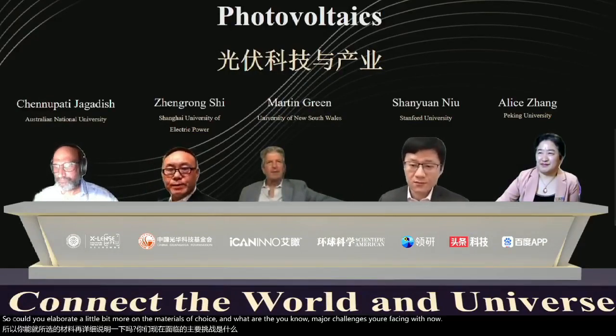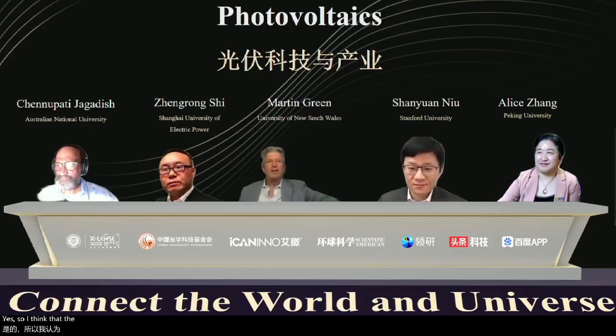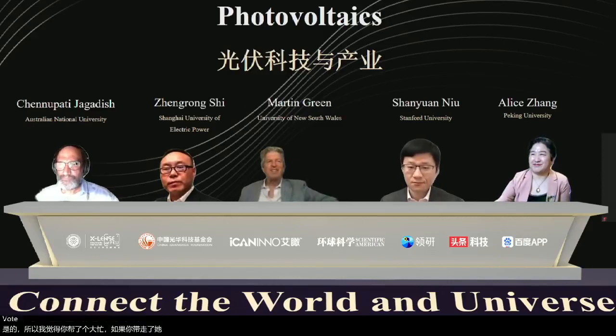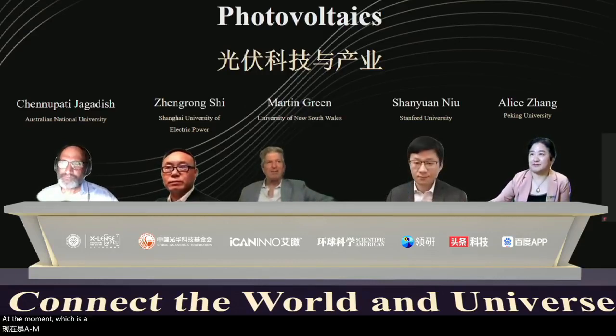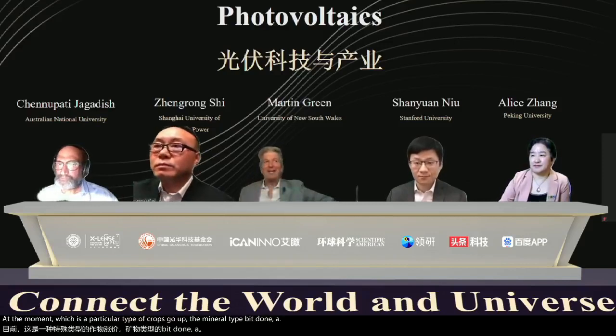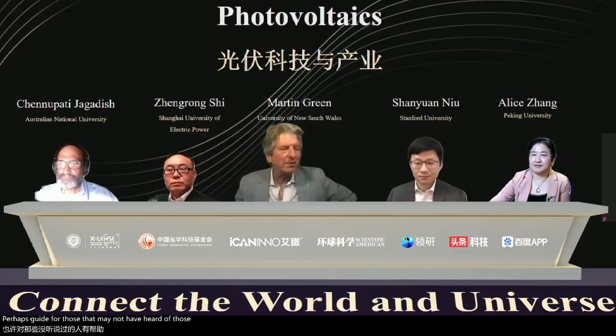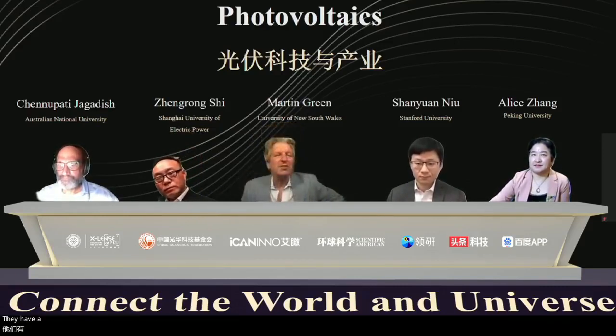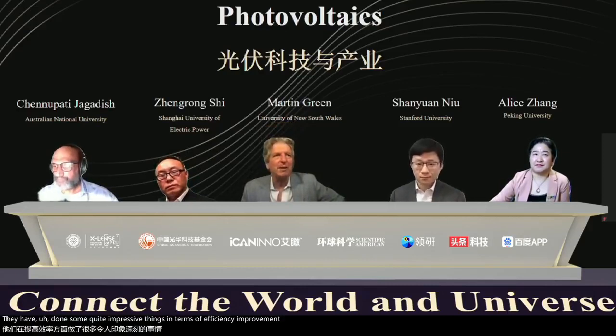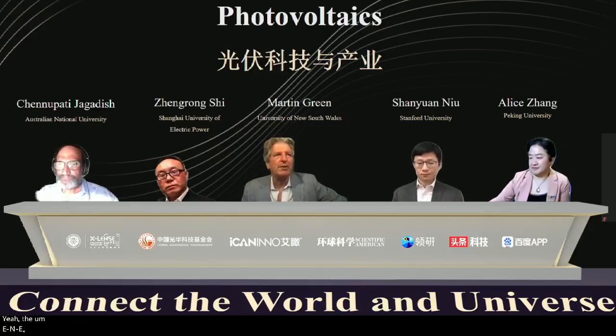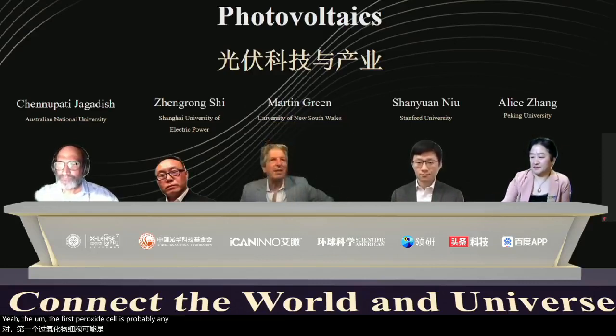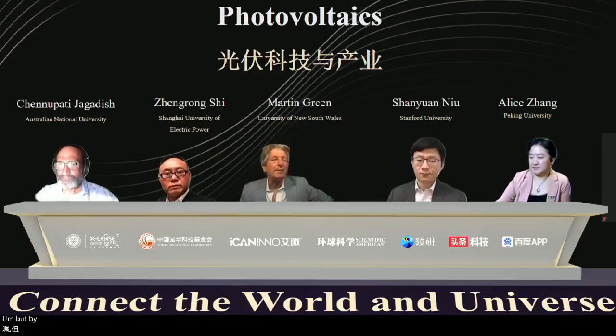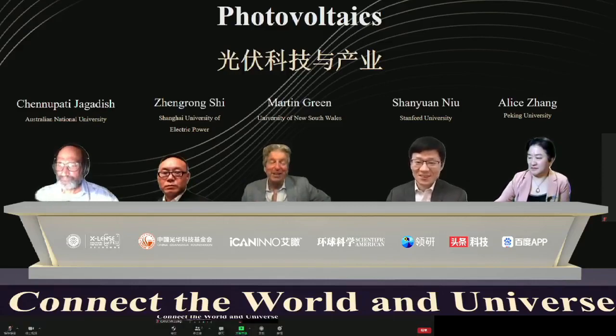Yes, so I think the hot favorite, if you took a vote amongst those working on photovoltaics, would be perovskites at the moment, which is a particular type of perovskite, not the mineral type, but a lead halide perovskite, for those that may not have heard of those cells. But they have done some quite impressive things in terms of efficiency improvement. The first perovskite cell was probably only reported in 2009 or so, but by this year they're already up to 25.5% efficiency. That's just unheard of in photovoltaics, being able to go from nothing to 25% over such a short period.